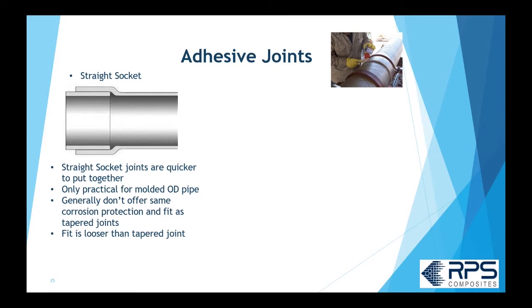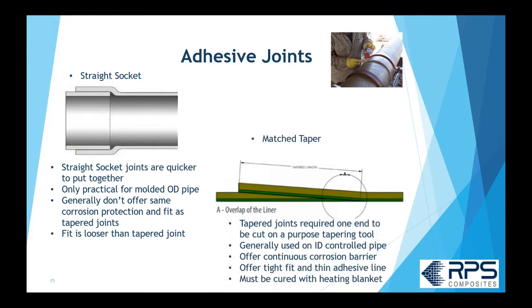So generally speaking, it doesn't offer the same kind of corrosion protection that you'd get from a tapered adhesive joint. And I'm going to show you that in a second, primarily because you have that thick edge and relatively loose fit. It doesn't have the same kind of tight fit that you're going to have with a tapered adhesive joint.